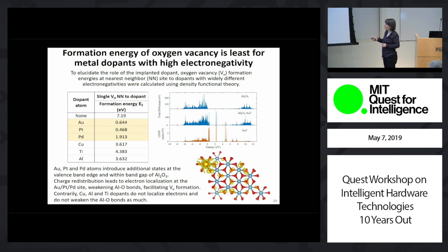Okay? And if we look at the electronic density of states, when we introduce these dopants into alumina, we find creation of these in-gap states that arise from gold, platinum, and palladium, not from copper, titanium, and aluminum. And these states localize around the implanted ion, in this case gold. And this electron localization then weakens the metal-oxygen bonds that then make it easier to remove oxygen from the nearby sites. Okay?